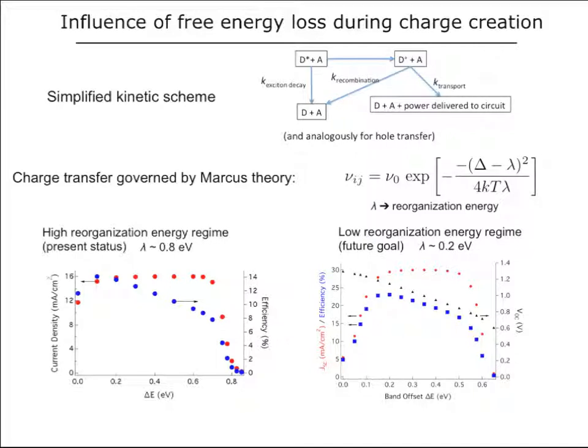However, and this is the new idea I want to bring to you, if lambda is very small, if we can make materials that have a very small distortion of the molecular bonds, this would happen if the bonds are very rigid, or if the donor and acceptor are lined up just in the right way, then we get a completely different plot. And in this case, the efficiencies now start at something like 10 for large band offset and go up actually above 20 for small band offset. So in the limit as we have small band offset and small lambda, we actually approach the Shockley-Queisser limit.